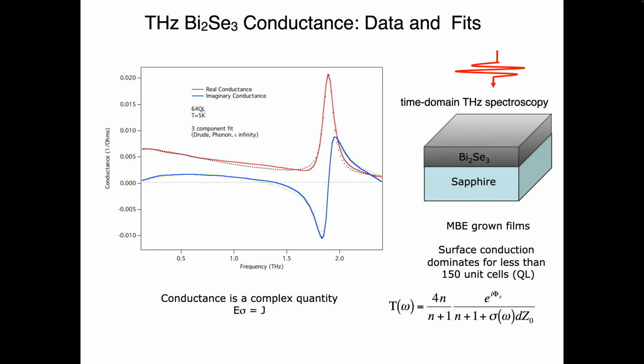So the red data is the real part, and the blue data is the imaginary part, and it's very textbook behavior for the kind of thing you would get for a metal. This is the topological surface state that you're seeing here. It's semi-classical response. So it has this peak at low frequencies that has a width of about 1 terahertz. So that's the rate that the current dissipates in the topological surface state. Here, I'm just thinking about the real part for a moment. And then there's this big peak that's at about 1.9 terahertz, and that's a phonon.